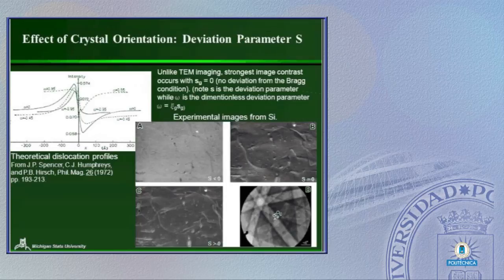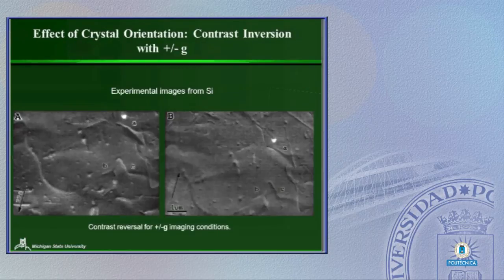This is a selected area channeling pattern that effectively shows the locations of the non-tilted beam, which gives us really what the deviation parameter is relative to this channeling band. And we can see when S is less than 0, the contrast is very poor. When S is equal to 0, we get strong contrast. When S is greater than 0, we maybe don't get a strong contrast, but we get a little bit sharper images. And so generally, we want to be in these kind of imaging conditions in order for us to be able to get the best image, best contrast, best resolution of our dislocations.